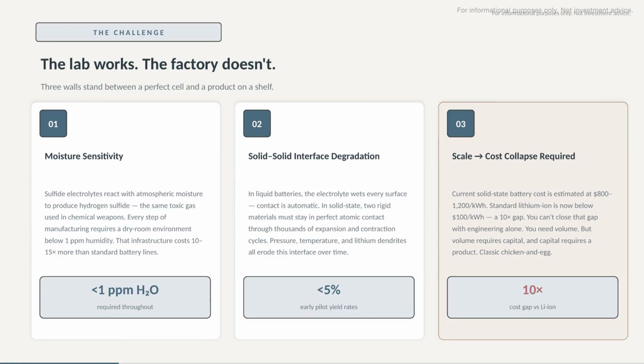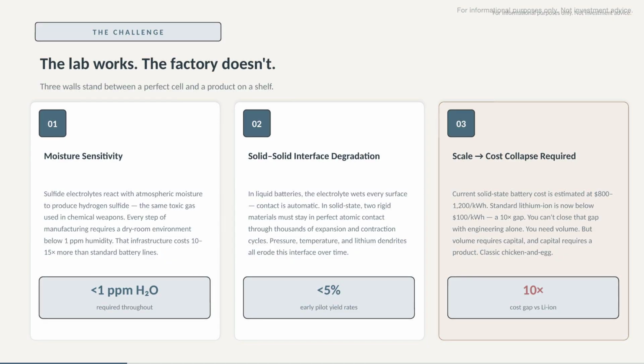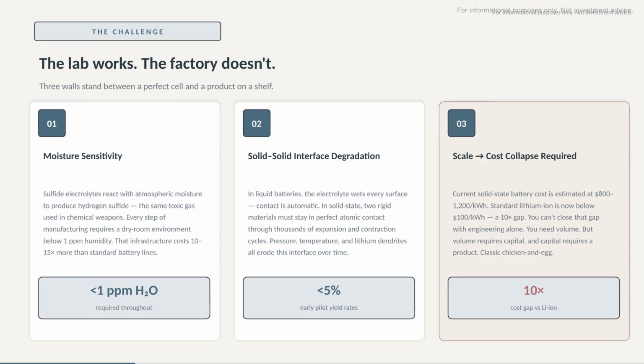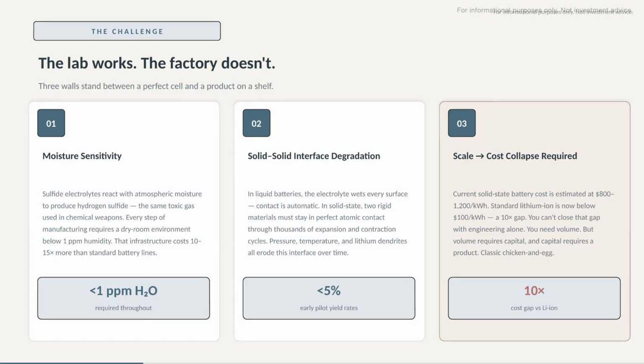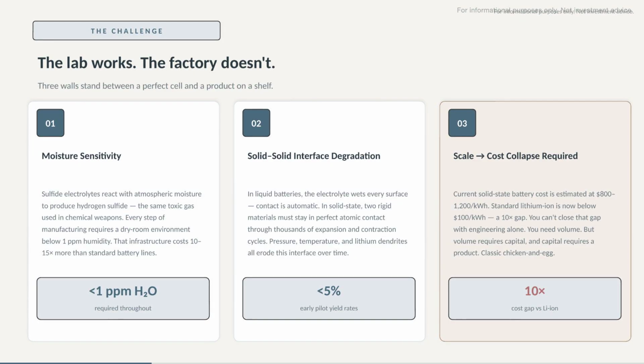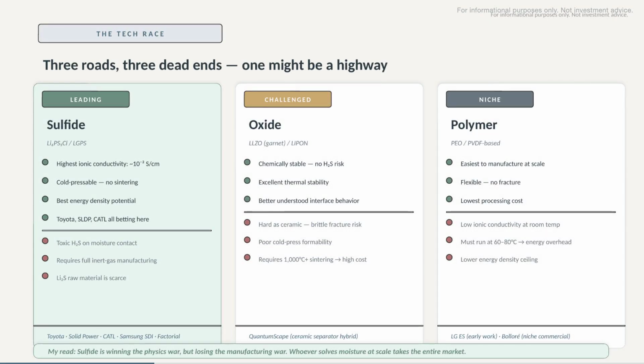Wall 2, solid-solid interface. Liquid electrolytes wet every surface automatically. Rigid solids must maintain atomic contact through thousands of cycles. Dendrites and pressure eat away at that contact over time. Wall 3, yield. Early pilot lines reported yields under 5%. You need volume to cut cost, but you need a product to get volume. Classic chicken and egg.